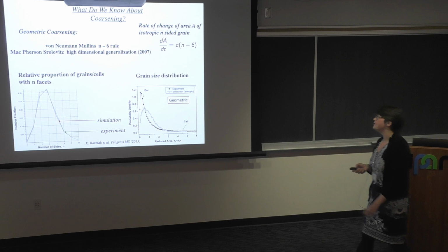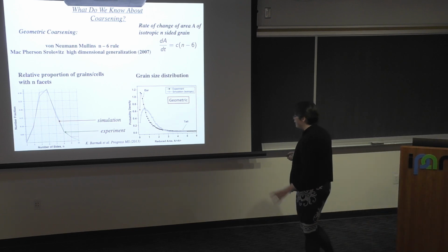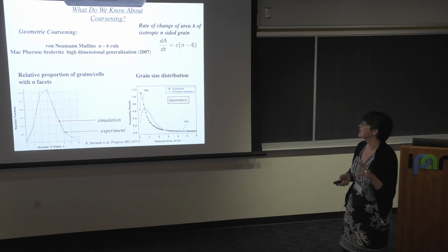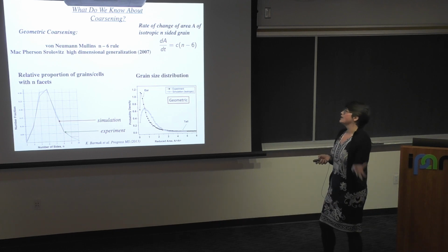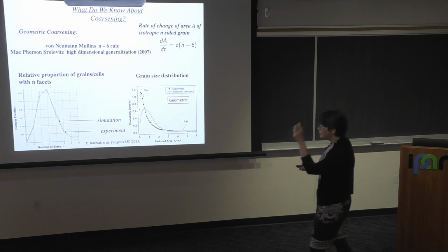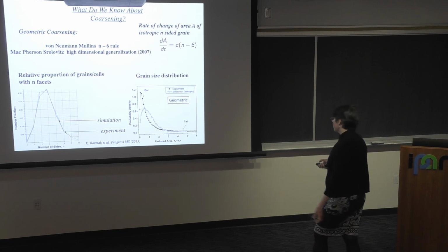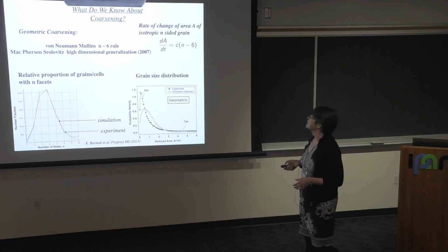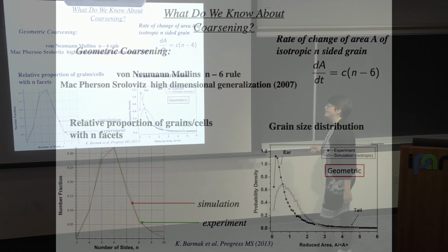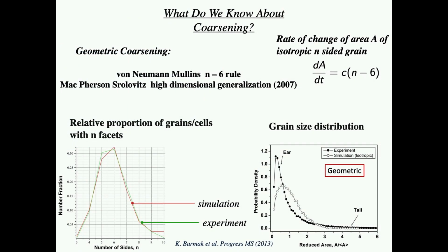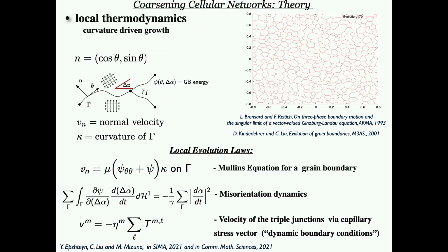From what we tried, we believe what affects that is how we model these disappearance events, or what we call critical or topological events, when grains disappear. But not only do grains disappear during grain growth, there are also rearrangements of sides and splitting of unstable junctions. I think we need more accurate, more physically sound models that capture these topological events more accurately, so we have better agreement with respect to this statistical metric. And we hope that in situ experiments will give us more insight into how to model these topological events more accurately.